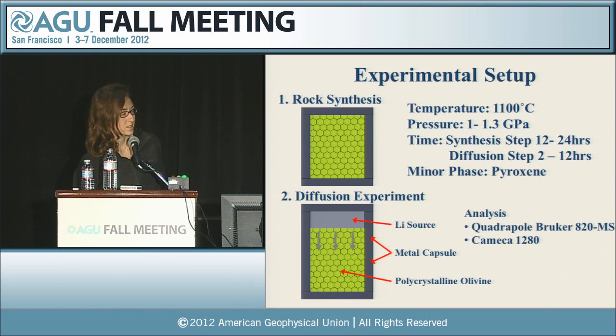So after this rock synthesis step, the capsule is sectioned perpendicular to its long axis, and that cut face is polished, and then that cut face is juxtaposed to a lithium source, in this case spodumene. So then the diffusion experiment is run at the same conditions as the rock synthesis step, except for shorter amounts of time. After the diffusion experiment, the capsule is then cut perpendicular to the interface between the source and the polycrystalline matrix, and is prepared for analysis by quadrupole ICP-MS or ion probe.